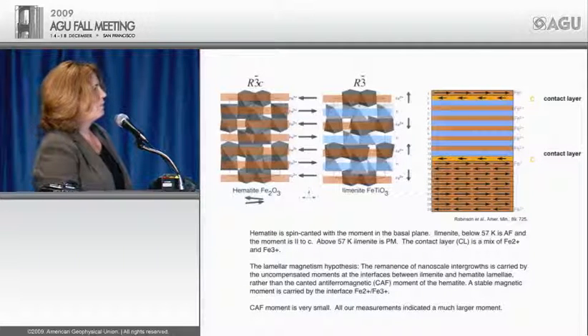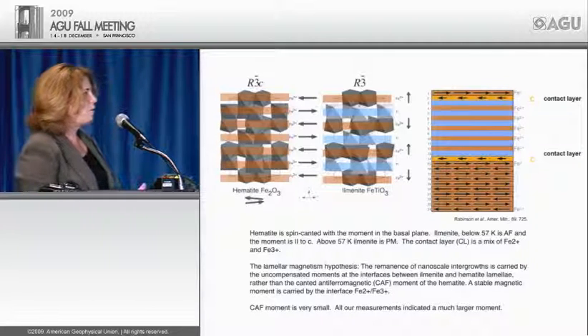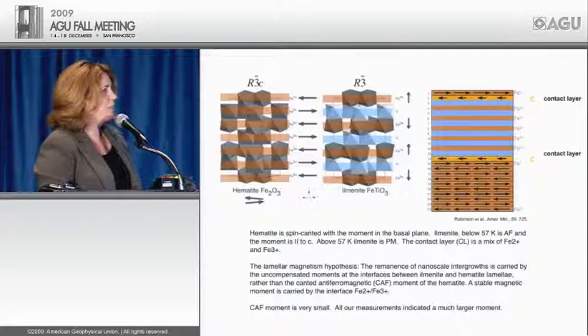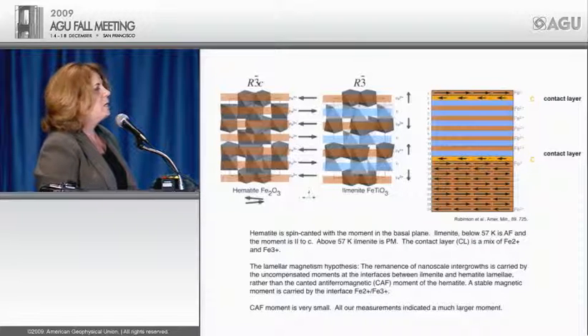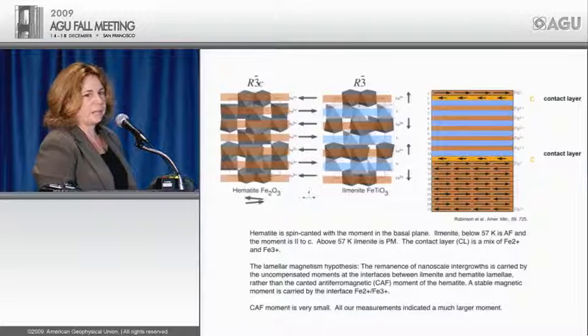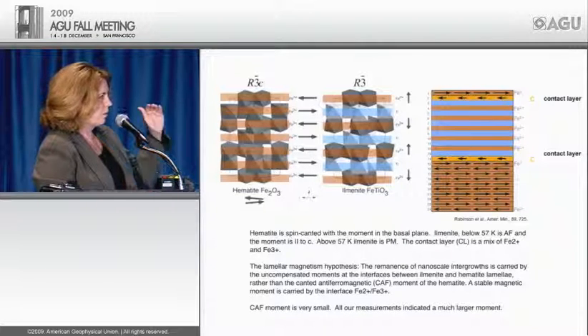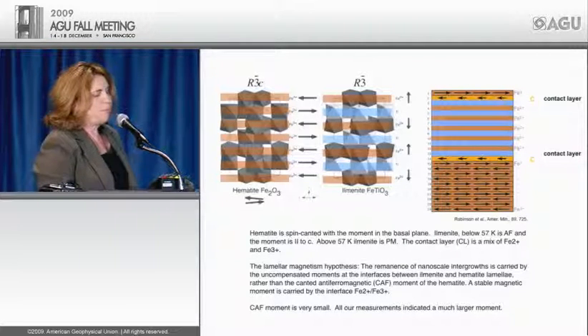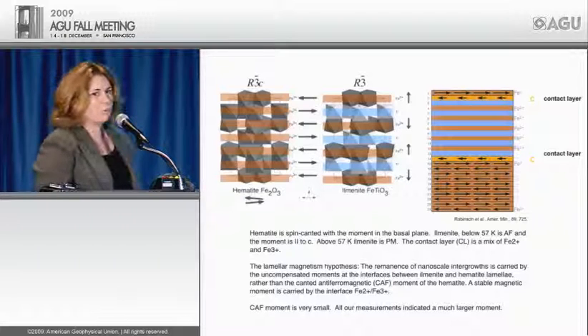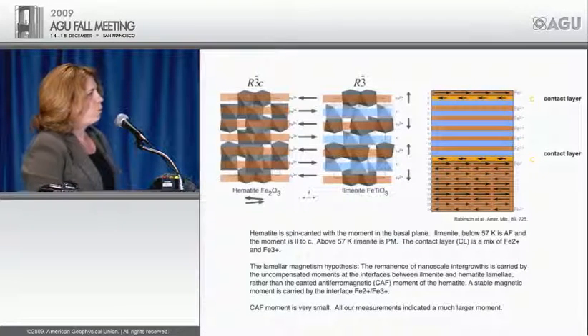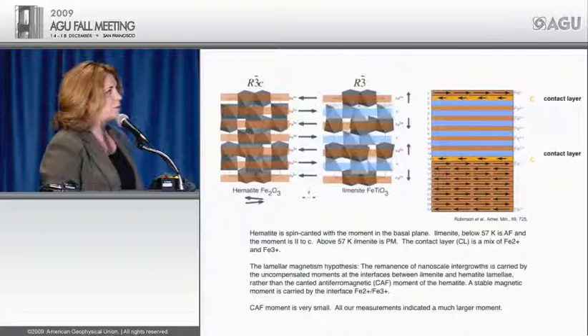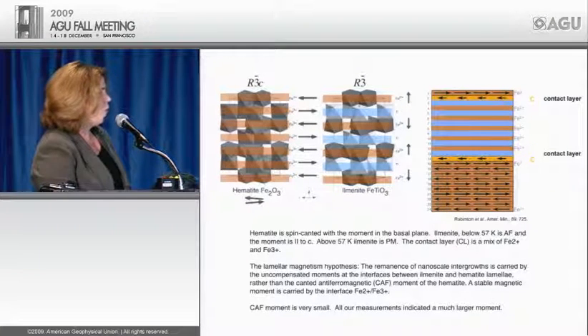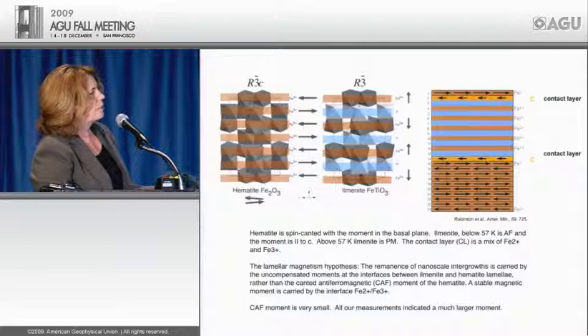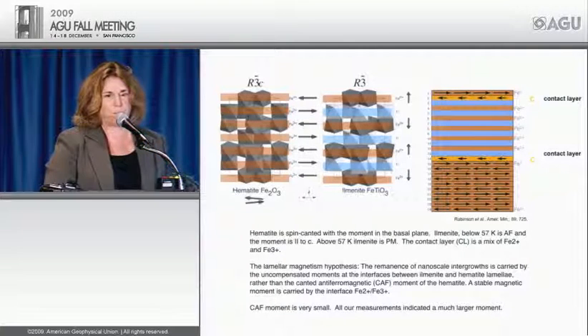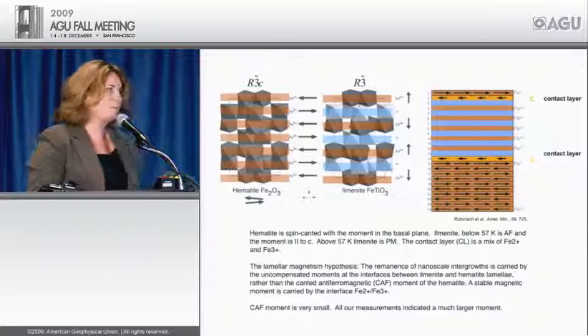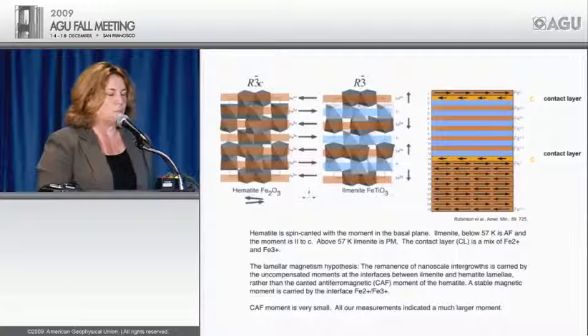Now, what is this concept of lamellar magnetism? What we have are two phases that are intimately intergrown. We have a hematite, which is a canted antiferromagnetic moment with alternating layers, and alternating AF moments pointing, Fe3 plus layers. In the ilmenite, we magnetize parallel to C, but this magnetizes only below 57 K. And what we found, or what we proposed quite a few years ago, was that at the interface between the lamellae, there's a mixed iron layer there, an Fe2, Fe3 plus layer. This is a substructure. This is not a separate phase. But this is what's responsible for the bulk of the magnetization.